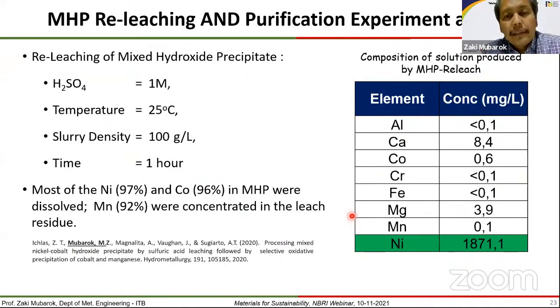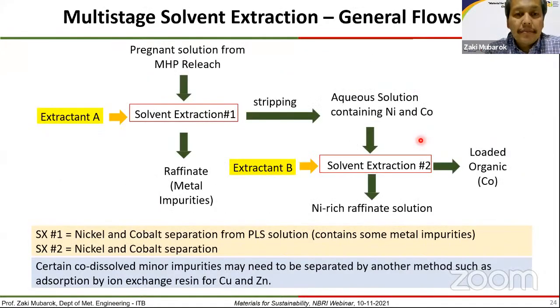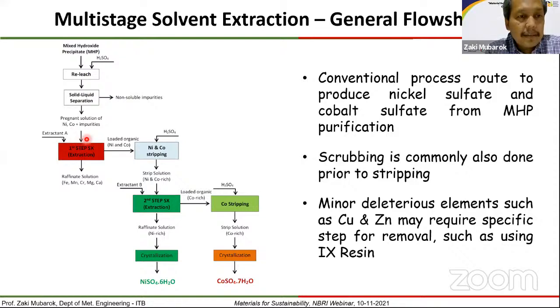And I come now to the process of purification of MHP to nickel sulfate. So we re-leach MHP at room temperature, with these parameters, and this is the concentration of metals in the solution obtained by MHP re-leach. And we do this quite conventional route, 2-stage solvent extraction, and the solution is subjected to the first step of solvent extraction to separate nickel and cobalt from iron, manganese, chromium, magnesium, and calcium. And then at the second step, we use another extractant to separate the nickel and cobalt, and we do crystallization,